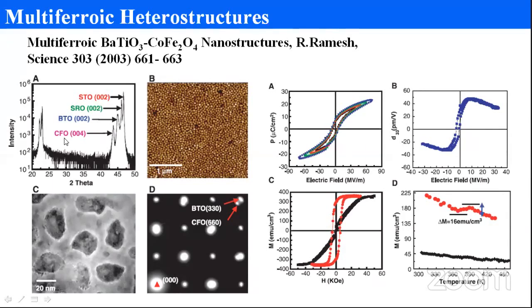Okay, so this is epitaxial. There are no secondary phases. That is very clear from this one. The TEM image shows a clear ordering of cobalt ferrite rods in a barium titanate matrix. And this is the SAED pattern, which clearly shows that these are all highly crystalline, barium titanate and cobalt ferrite.